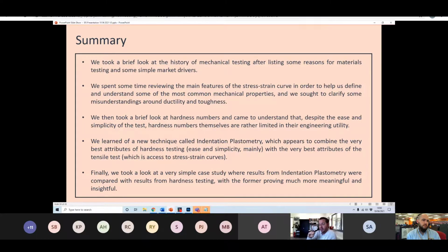And you can start to build up a profile of what the stress strain curve behavior looks like the deeper you go. And what we would expect is the deeper you go, eventually those stress strain curves will start to converge and fall upon a single stress strain curve as eventually you start to essentially interrogate mostly just the underlying layers, the underlying bulk mechanical material. That's what I mean. So lots to think about there. But again, happy to pick this up with people independently if helpful.